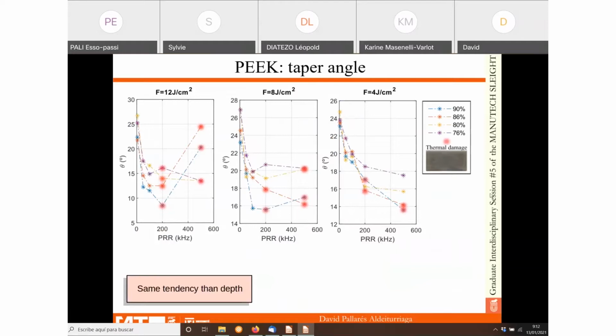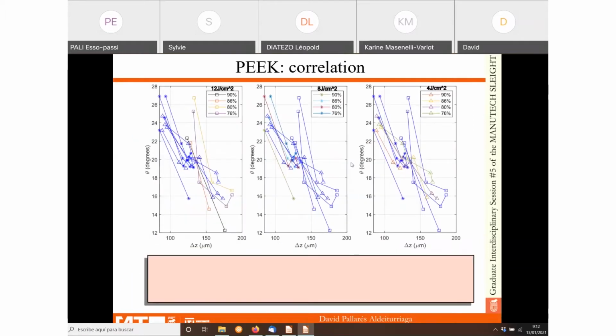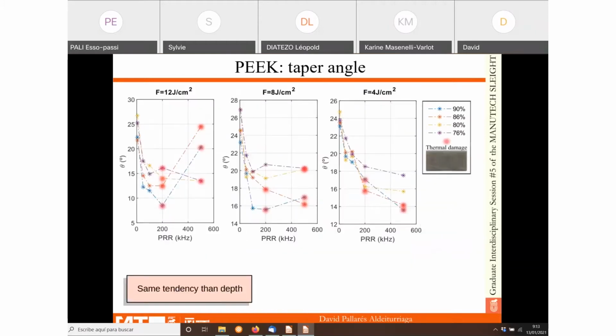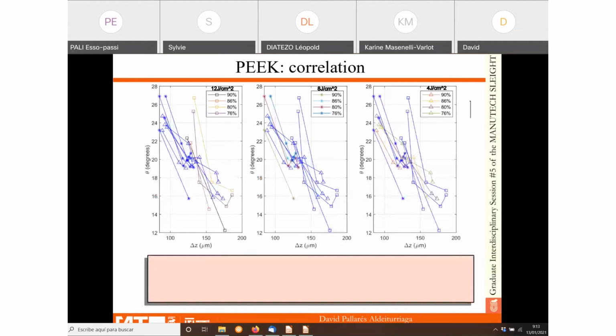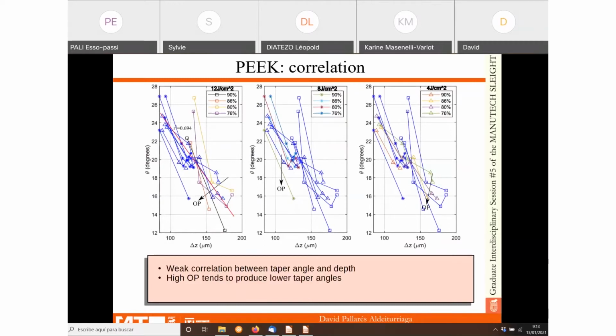This can also be seen with the taper angle. Okay, the same tendency. If we plot these two values, then we have a low correlation that, even if it's low, tells us some information: at high overlap ratios, we get low taper angles for the same depth, which is interesting because then we have sharper inscriptions.